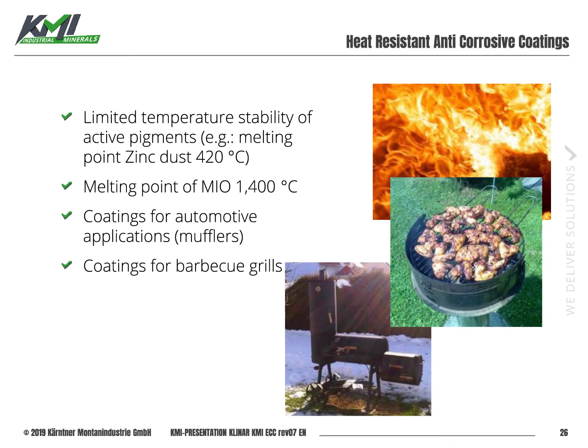Micronized MIO can also be used in heat-resistant anti-corrosive coatings. Here we speak about silicone-based coatings with working temperatures of up to 550 degrees C. The reason for that is micaceous iron oxide has a very high melting point of 1400 degrees C, which is far away from any limits of the resins.